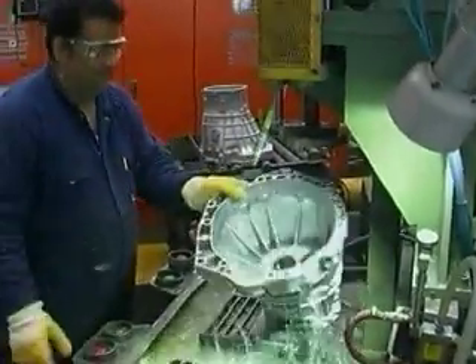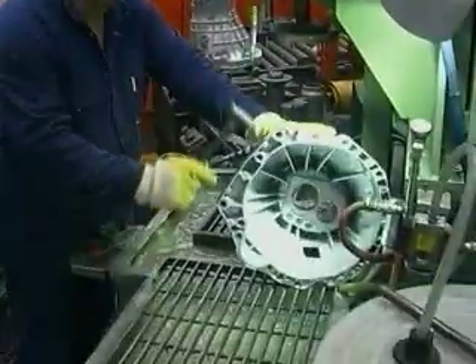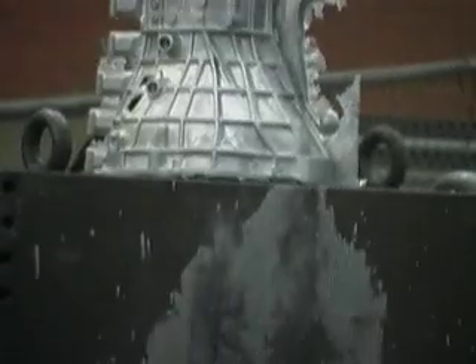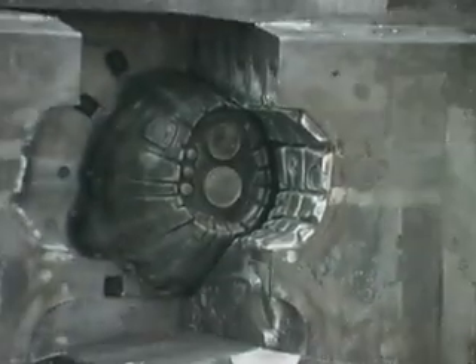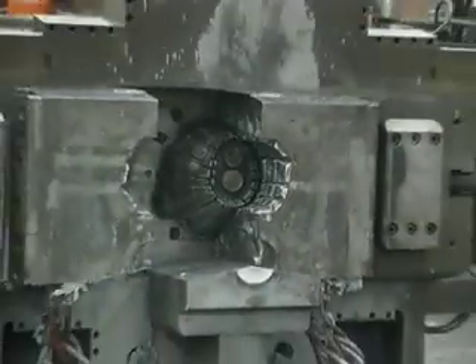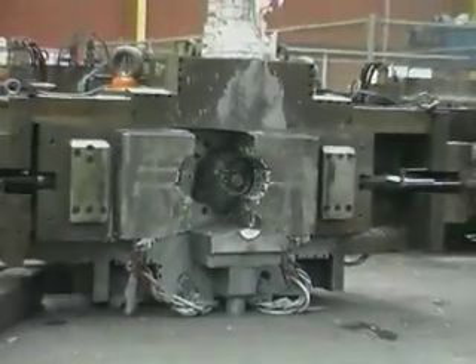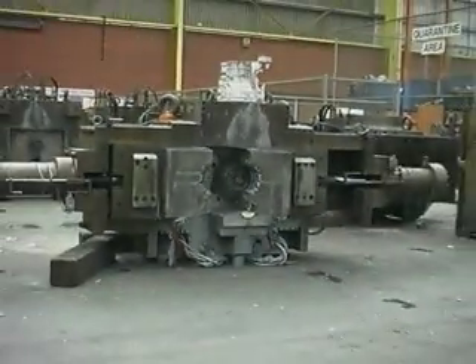This gearbox casting is 100% pressure tested for soundness, and 1 in every 100 is checked radiographically for any internal defects that might have arisen during casting. A die set to produce this casting has a cost in the order of $500,000. This means that each shot costs $2 to $3 in die wear alone.